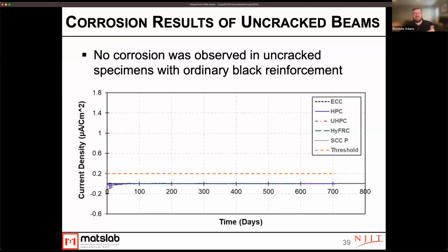So what we noticed really is across the board on our uncracked specimens, up to 700 days, so about 2 years, we have not seen corrosion begin on any of these samples. So we're still monitoring these. These are still in the lab, but this is why this test method tends to be a little bit slower. It certainly was longer than the project before we're going to see anything. So this is why it was important for us to look at some cracked specimens.